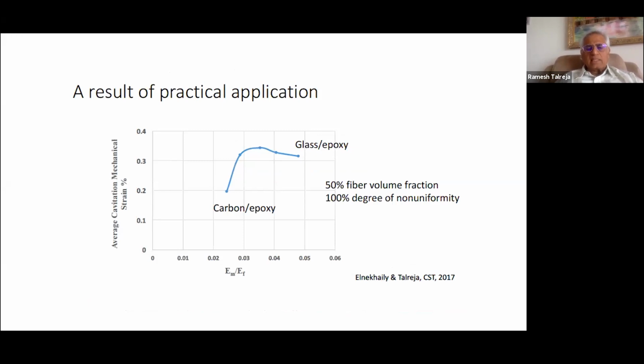also of interest. It's approximate because it should have been 3D, but it's 2D. But anyway, I think it qualitatively explains a certain feature that is not intuitively obvious. If I use glass fibers in epoxy versus carbon fibers in epoxy, for the same clusters of fibers, the initiation of dilatation induced cavitation is earlier in carbon because of the high stiffness mismatch. Now, carbon fiber is believed to be good in every sense, but that is really not the case here. So that's something also to point out.